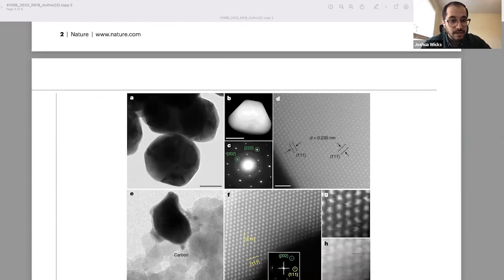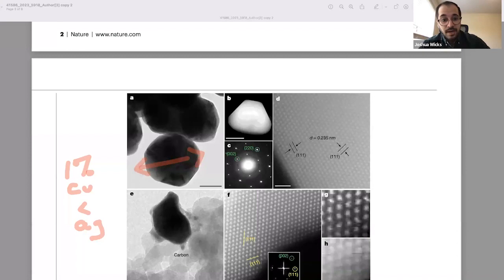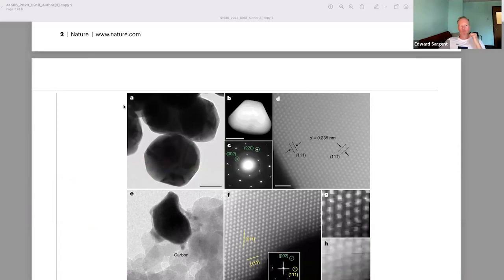Yeah. So now using nanoparticles as our structure of interest here, nanoparticles around 50 to 100 nanometers in size. These nanoparticles are primarily silver in structure composition with roughly 1% copper doped inside in an even distribution throughout the material. We used a wide variety of characterization techniques, specifically advanced TEM measurement techniques, led by colleagues at Northwestern University, Xiaobing Hu and Vinayak Dravid. And so we used these to identify some of the exposed facets along the material, which were consistent with the facets that we were using in our density functional theory calculations, and as well to better assess the composition of the material therein.